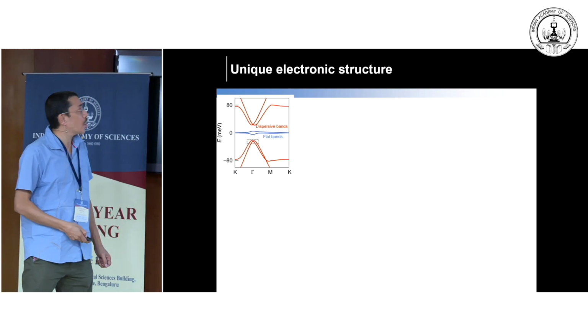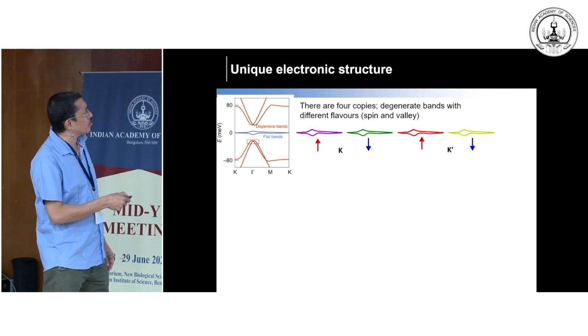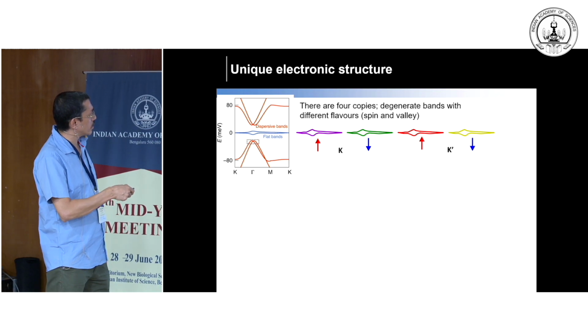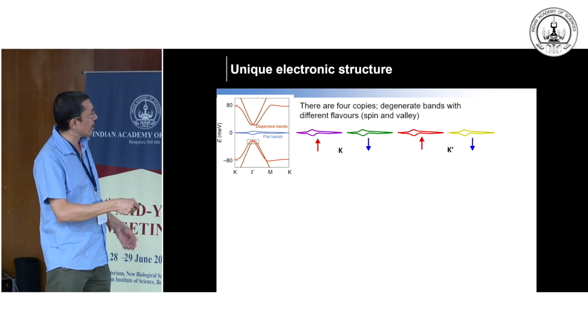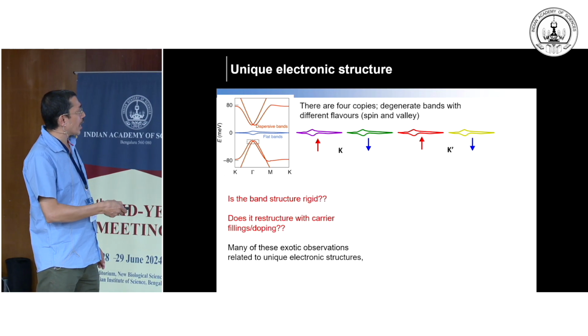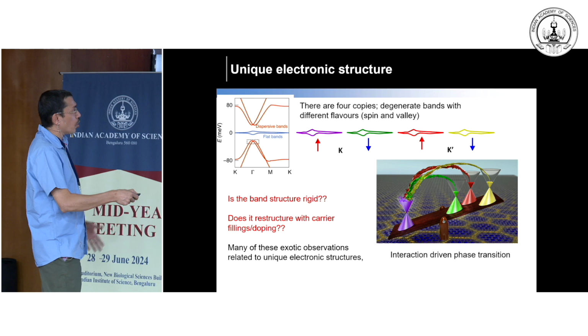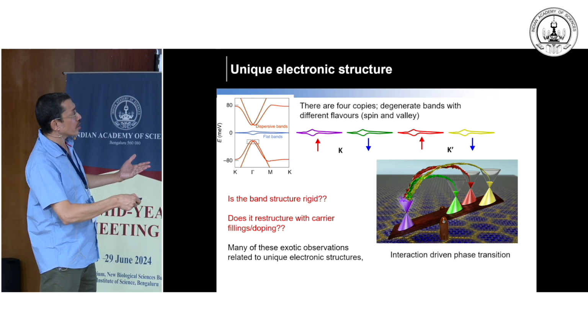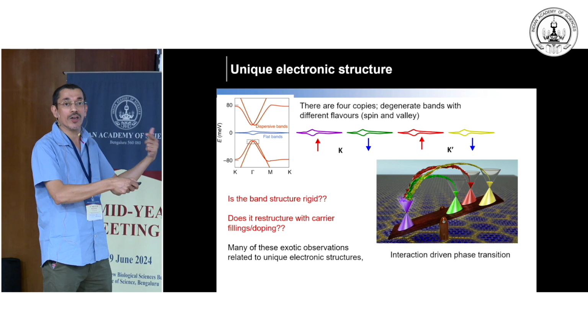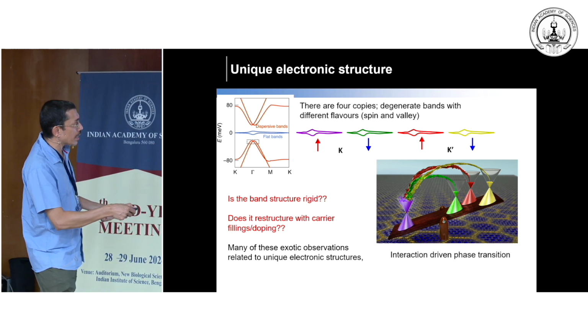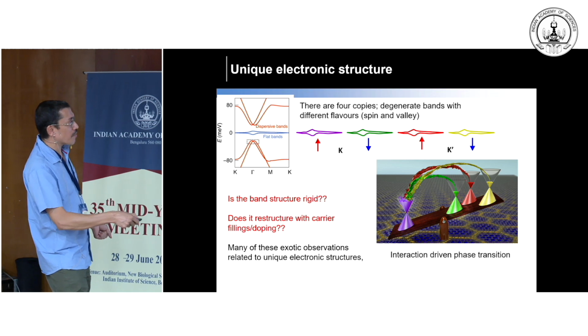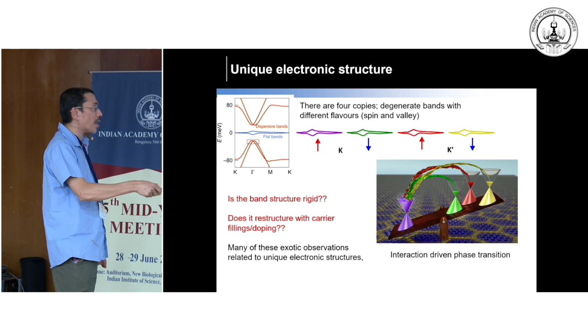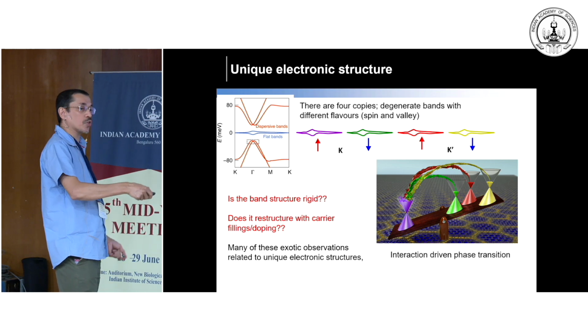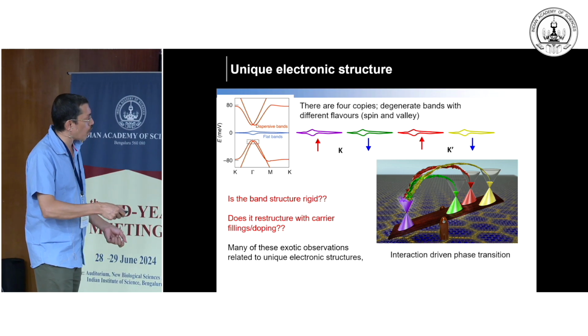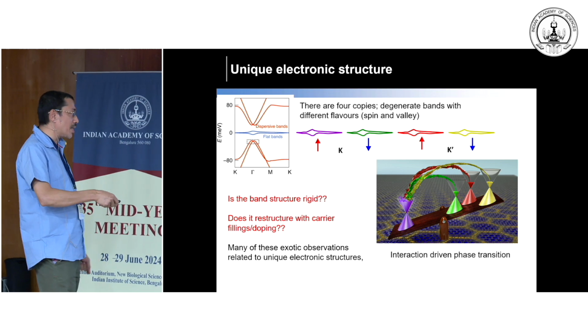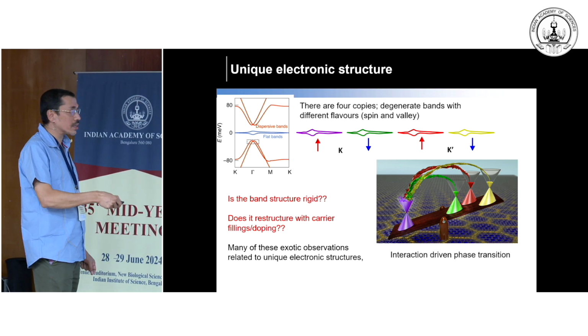Now the question is, not only that, there are unique features of this electronic structure. What has been shown is that this flat band has 4 flavors, which I was talking about, that are 2 spin and 2 valley. And more importantly, this cartoon picture shows that although you assume that if I fill the carriers, all the 4 flavors are supposed to be filled equally, in reality what happens when I fill the carrier, suddenly one of the flavors, here I have shown like 4 glasses filled by water, the 4 glasses are supposed to fill equally, but in reality what happened, one of the glasses or one of the flavors gets filled up, and this is because of the interactions.